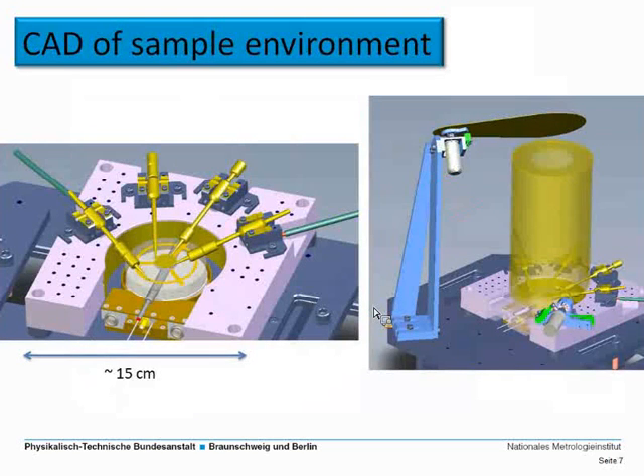So in the CAD of the sample environment, this looks a little bit more elaborate, but I guess you can recognize most of the crucial elements. Again, we have the sample disk, the reference plate with the gold pattern, those clamping arms with the wires going out here, the heating module, and this entire thing is surrounded by a MACOR ceramic block, which is used to mount the individual components and also acts as a thermal shield because it has a low thermal conductivity. In case you're wondering how big this is, it is roughly 15 by 15 centimeters, so it's pretty compact. And in addition, we also use this gold-coated metal cylinder as another heat shield against thermal radiation.